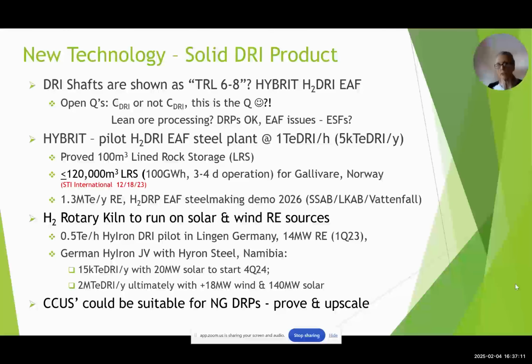We also have hydrogen rotary kilns that can run on solar and wind renewable energy sources. There's a 0.5 ton an hour HyIron DRI plant in Germany running on 14 megawatts of renewable energy since the first quarter of 23. They're going to do a joint venture with Hiron Steel in Namibia with a 15,000 ton a year DRI plant, 20 megawatts of solar to start with at the end of this year. And there's 2 million tons of DRI per year ultimately, with 18 megawatts of wind and 140 megawatts of solar. CCUs could be appropriate for DRPs if they're proven and upscaled.